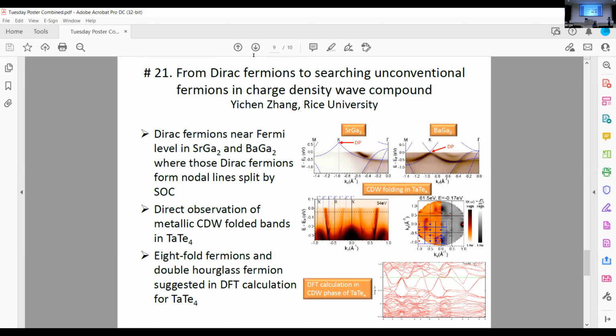Also, beyond these Dirac or Weyl fermions, solid state systems can also support higher order unconventional fermions like 3-fold, 4-fold, 6-fold, or 8-fold in lattice systems. We use angle-resolved photoemission spectroscopy to study the charge density wave compound tantalum telluride 4, where we directly observe the charge density wave for the electron pockets near the Fermi level. Theory also suggests that there is an 8-fold fermion at the A point and also a double hourglass fermion around high symmetry directions. If you want to know more details about the experimental results of these two systems, you can come by my poster session.